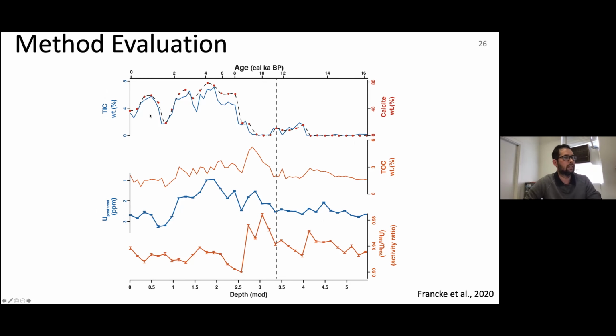And this is basically the same record again. We have uranium isotopes, uranium concentrations, organic carbon, and just for orientation, I plot the calcite content here in the upper panel. And one might say, okay, I have these high activity ratios here during the early Holocene. There's also high organic carbon content. Maybe that's all driven just by these high organic carbon contents.